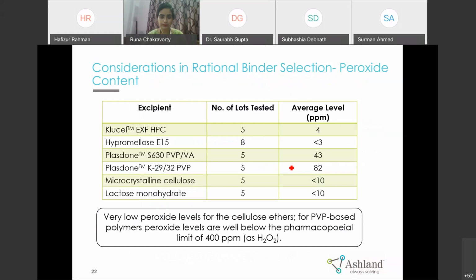So this is about the peroxide content, which we can see in different binders. Peroxide level matters because it can trigger hydrolysis and oxidation. So if your API, your drug, is sensitive to peroxides, in those cases we always recommend using a binder or other ingredients with a low peroxide level. If you compare peroxide levels, Klucel has much lower, negligible, around 4 ppm, when compared with the povidones, Plasdone povidone or copovidone, where the peroxide level is very high. So we can say it can give better stability to the product.